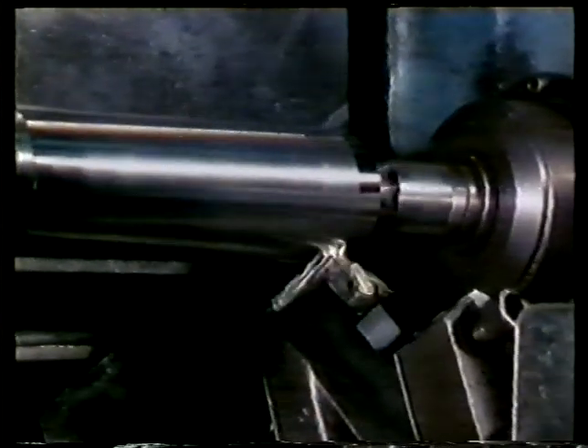Ceramic tools are used mainly for finishing cuts at high speeds and fine feed. Cutting speeds of up to 300 meters a minute are quite common. Under these conditions, ceramics can produce excellent results. But because of their brittleness, they are seldom used for intermittent cuts. This is due to the high forces involved, which can cause the tips to shatter.